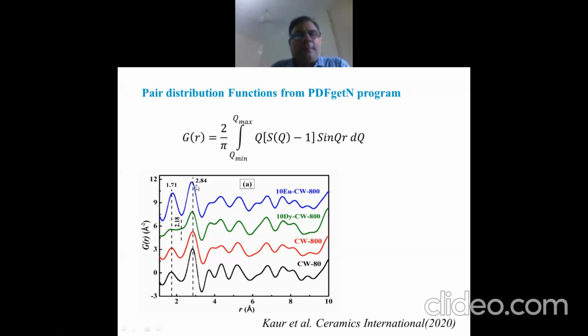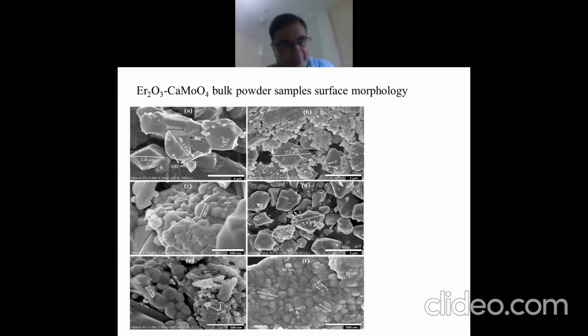So these are the surface morphologies of calcium molybdate particles doped with erbium oxide, and the particles are fairly big, and we also see some morphology which has definite angles. These calcium molybdate materials doped with erbium oxide show both up conversion as well as down conversion. In an up conversion process, you convert long wavelength light like 980 nanometer to green light, whereas in down conversion, you convert UV light like 380 nanometer light to green light, which has a wavelength of about 560 nanometers.